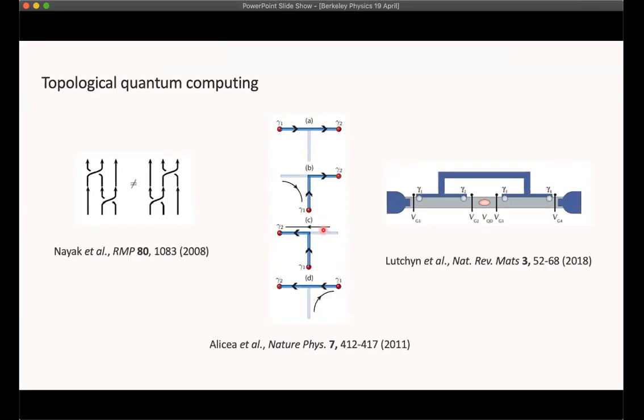And so throughout this process, I didn't bring them close together to interact. In fact, I kept them relatively far apart, but I nonetheless achieved the topological braiding operation that I needed. Now, I'll note for the experts that this kind of operation, which is actually at the heart of building a topological quantum computer, is also possible not with braiding, but with projective measurements of the parity, in this case, of the anyons. So if I had two of these wires, and I had these anyons at the end of each wire, I could put some sort of quantum probe between the wires.